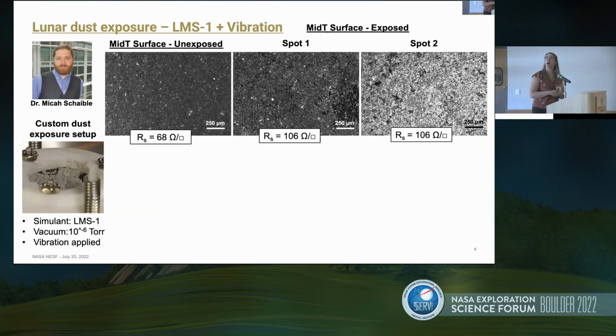So if we look at a composite that's processed at a middle processing temperature, so this is a partially infiltrated composite, on the far left is the unexposed. So you can see there's a lot of surface variation. That sort of indicates that there's roughness and porosity where we think that grains could be trapped and abrasion could occur. We do have fairly good surface resistivity. This is orders of magnitude more than what we need for static charge dissipation at 68 ohms per square.